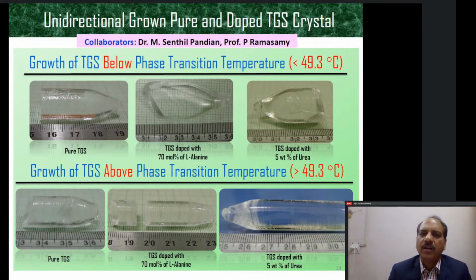That crystal, because all the device applications are in the ferroelectric state. So we thought that if we grow only above the phase transition temperature, then we may not be able to make a comparison. So we thought we will grow TGS above the phase transition temperature, and similarly, simultaneously, we will grow another crystal below the phase transition temperature. So we did two different experiments on pure